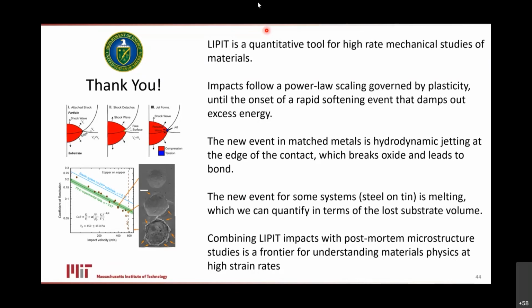We can. So, in fact, as part of our work with Livermore, we did some things where we tried to slow it down, and we can get the velocity down to a few dozen meters per second, which gets you into the same velocity range as some other micromechanical tests. But our strain rate is still a few orders of magnitude high because we're so small. So it is a significant research project to get between 10 to the 7th and now 10 to the 4th, where like a Kolsky bar would hit, right? So there's a 3 order of magnitude gap there, which I think there's some innovation needed.